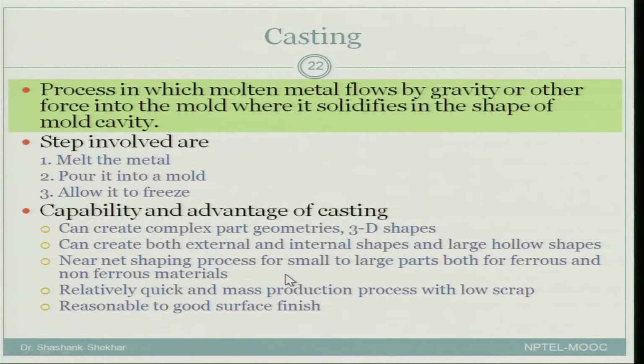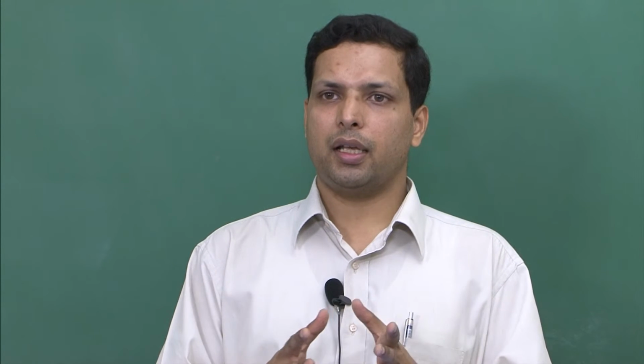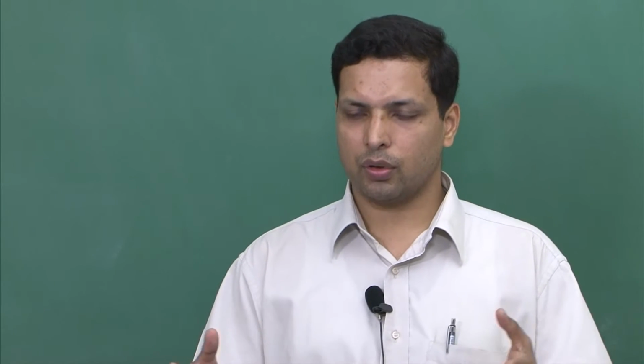So it is not that casting is only limited to ferrous metals, which is actually a very big class of metals. You can also get non-ferrous metals, and we have already seen the examples, the brass and the aluminum alloys. Another thing is that it is relatively quick, and mass production can be done with very low scrap. Because whatever scrap is there, you can put it back into the melt and reutilize it. And all you need is basically, let us say, a wooden pattern. And if you have a wooden pattern, as I will show you in the next slide, you can make the mold around it, and in that mold you can get the desired shape.